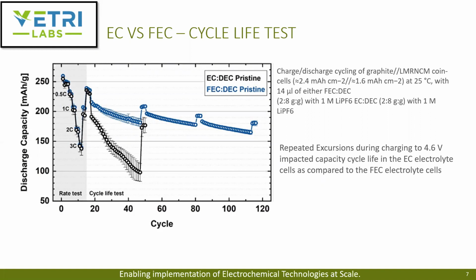In this case, the fluorinated ethylene carbonate outperforms the ethylene carbonate. The discharge capacity fade is much faster, losing about 50 to 100 milliamp hours per gram within 50 cycles, versus being at least 2.5 times better with the fluorinated ethylene carbonate system.